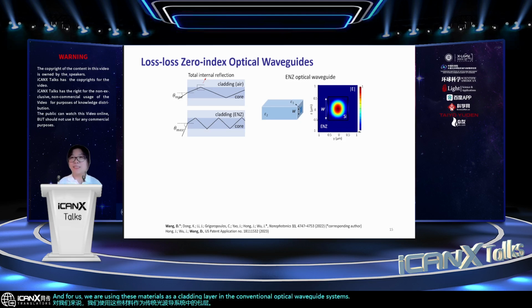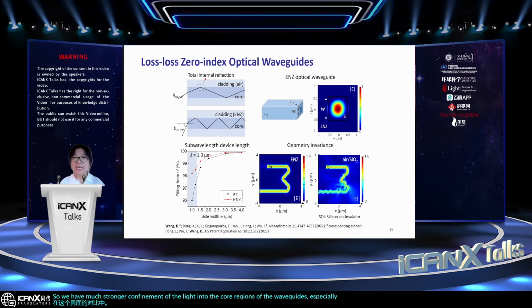What we found is that because of this extreme dielectric index contrast at this interface, we have much stronger confinement of the light into the core regions of the waveguides, especially when the device size is below the wavelength of light. We found that our system has a much stronger confinement of the light to the core with minimized loss.